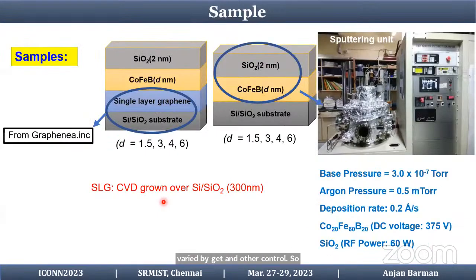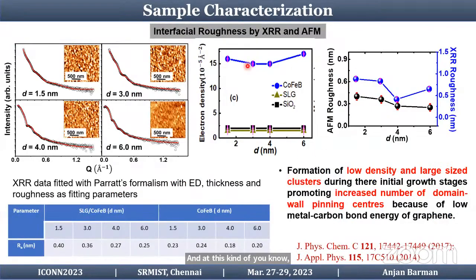So we grew graphene, we actually procured graphene from Graphenea, and we grew a cobalt iron boron layer on graphene at this kind of pressures and all. And we characterized the interfacial roughness using X-ray reflectivity and atomic force microscopy and so on. And it shows that the values are fairly low, that is, the interface is quite good.